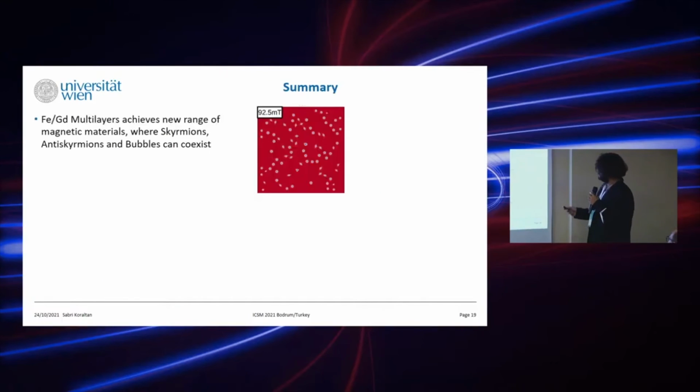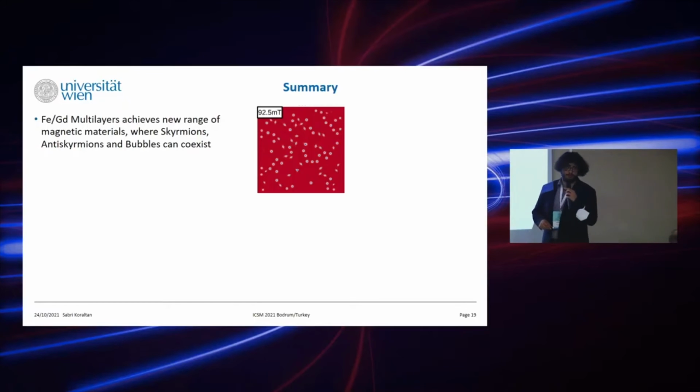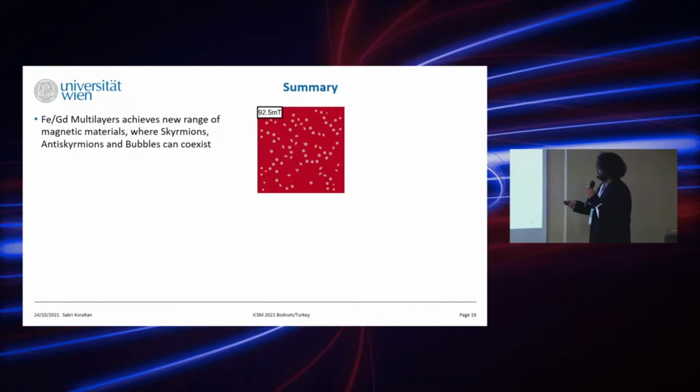As a quick summary, we have investigated iron gadolinium multilayers, where by the insertion of additional iridium layers, we were able to reduce the magnetic parameters in such a way that skyrmions, anti-skyrmions, and trivial type 2 bubbles were dipolarly stabilized. And we have basically proved their coexistence.